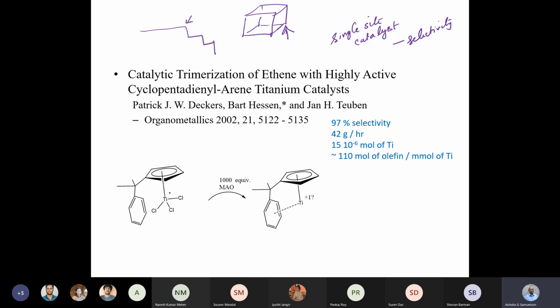So here is a titanium catalyst, and the titanium catalyst was generated starting with titanium tetrachloride, but with replacement of one chlorine with a cyclopentadienyl group, and the cyclopentadienyl group had a pendant aromatic ring system, and that can coordinate to the titanium once these 3 chlorines are removed. How do you remove these 3 chlorines? You use something called MAO. MAO is methyl alumoxane. I'll come to the structure in a minute.